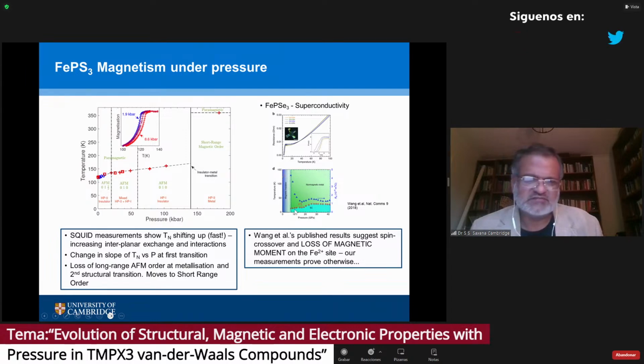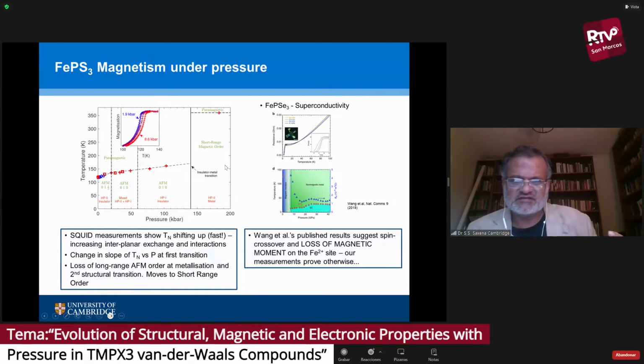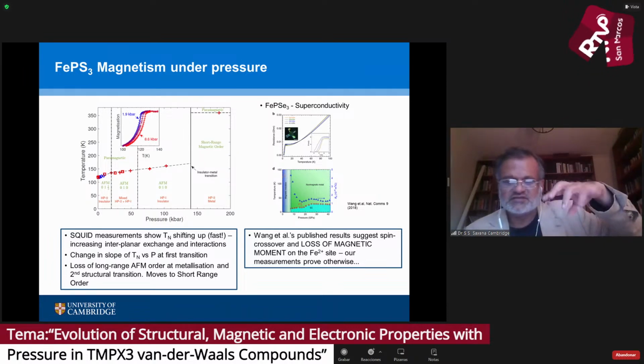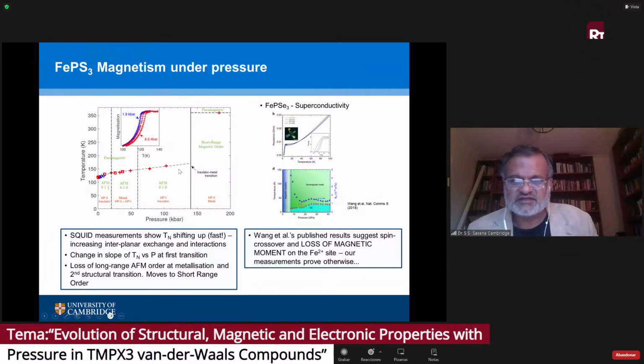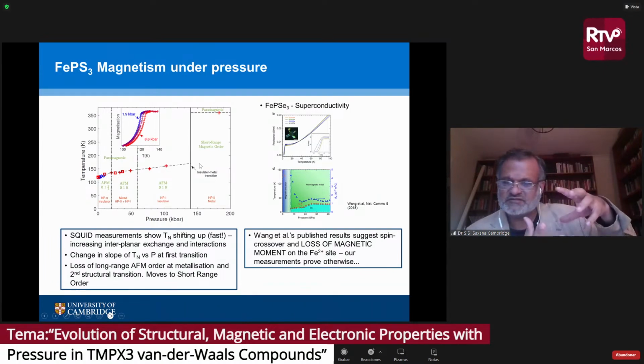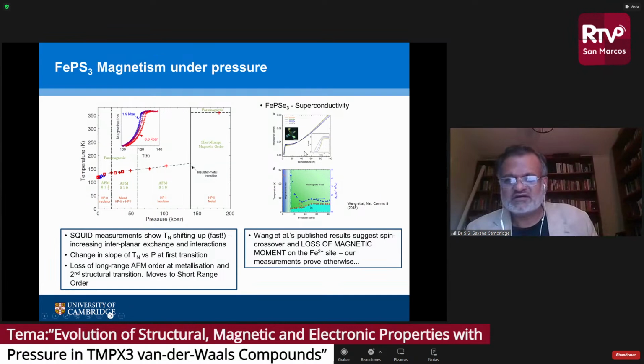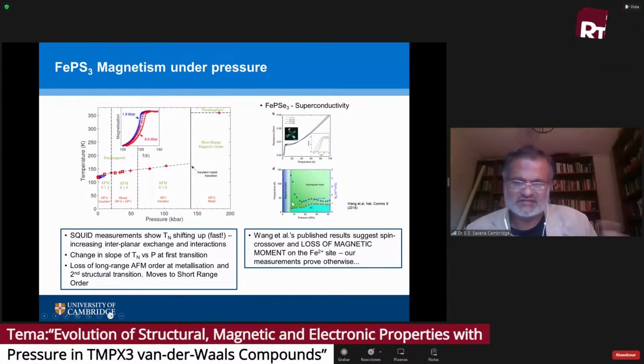and goes superconducting. This could be a simple explanation, but there could be a more evolved way of thinking about it, and that is the size of the atom, sulfur versus selenium. The odd thing that happens here is, you go from a 2D insulator to a more 3D metal, because van der Waals collapse makes it more 3D. So the fact that this material perhaps becomes 3D more quickly, before the 2D nature of the system can find superconductivity in itself, while this can happen in this material, but we still have magnetism to explain. So this is still an exciting area to investigate, and that's what we're doing.